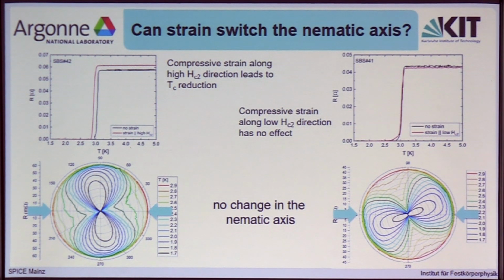Interestingly, there is no reduction in transition temperature for the other sample, and we've conducted a second set of samples, and they show the same result. The reduction in transition temperature is only when we have compressive strain along the high Hc2 direction, and we see no change for compressive strain along the low Hc2 direction in both sets of samples. Now, this either tells us that with the strain that we are able to apply, we're not able to counteract the internal strain of the sample and switch the nematic axis, or maybe there's a totally different mechanism at play in these samples here. So with this, I would like to conclude my talk.